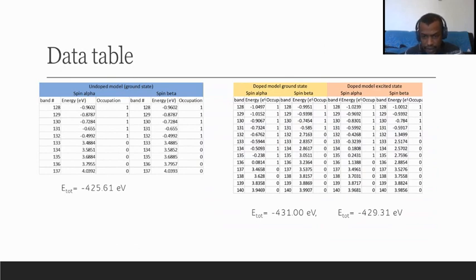And then in the second one, we can see that N up down is equal to 5, because from 132 to 136 in the one that's yellow, we have occupation in the alpha spin orbital, but no occupation in the beta spin orbital. That would be directly connected to manganese contributing 5 electrons in the d orbital, which are having higher energy.